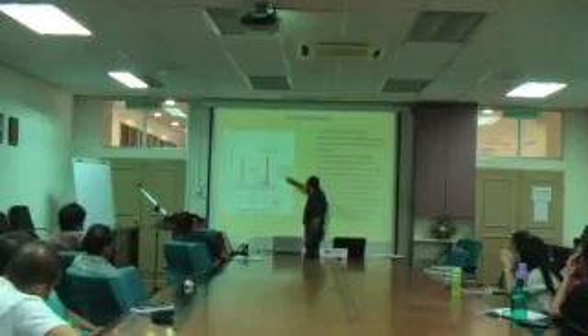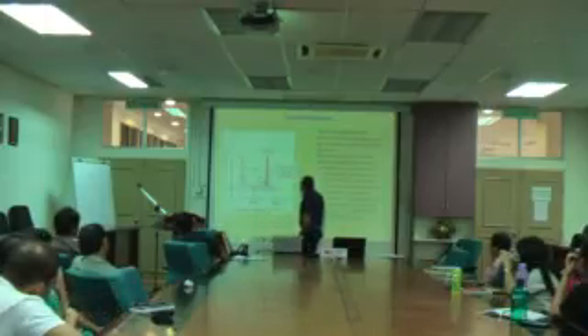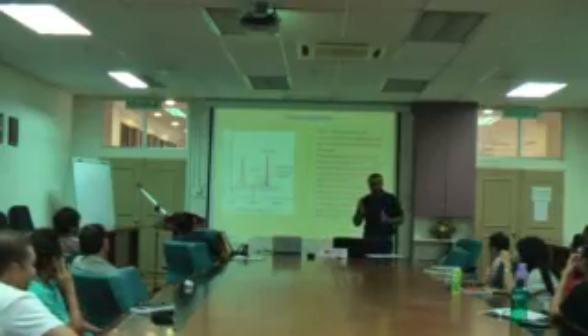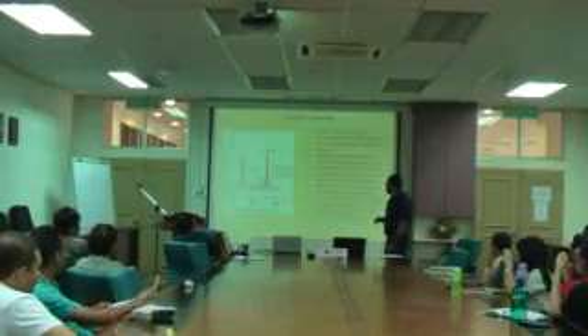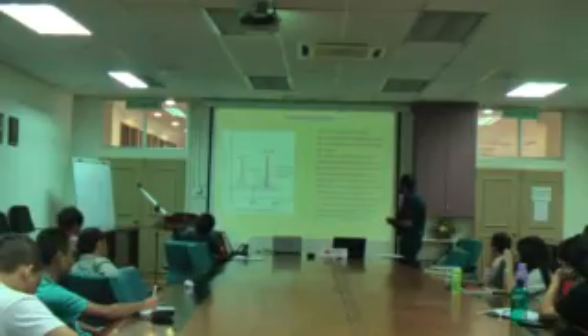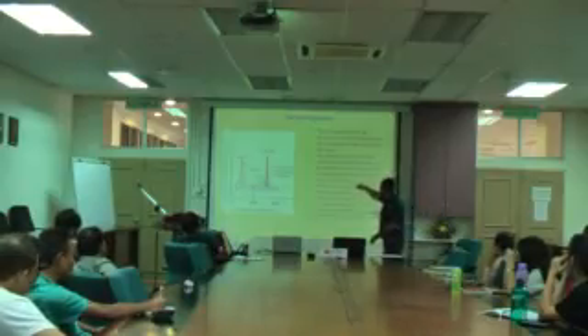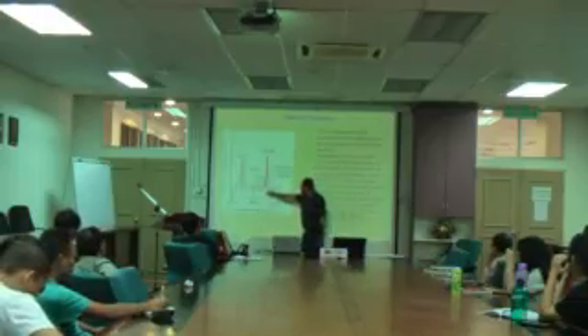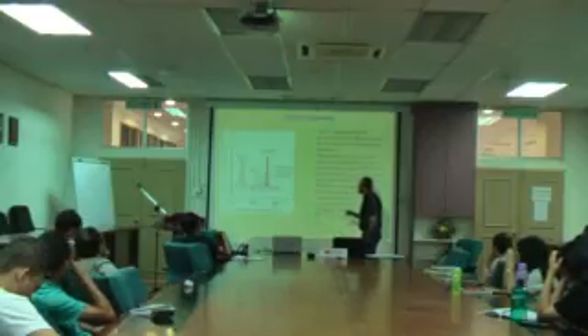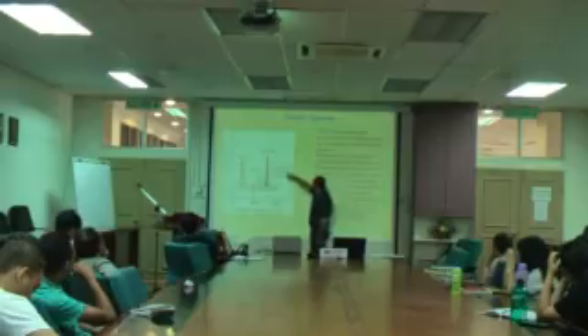But by increasing the silicon oxide intermediate level, the germanium peaks increases. Raman's increasing peak intensity is also exactly like XRD, related to the more crystallization of the samples. Because for bulk, the Raman is very sharp and intense peak. So going from 5 nanometers to 15 nanometers, germanium intensity increases. Of course, this one remains same because this is a bulk substrate. But also the interesting thing is decreasing the silicon germanium peaks by increasing the silicon intermediate layer.